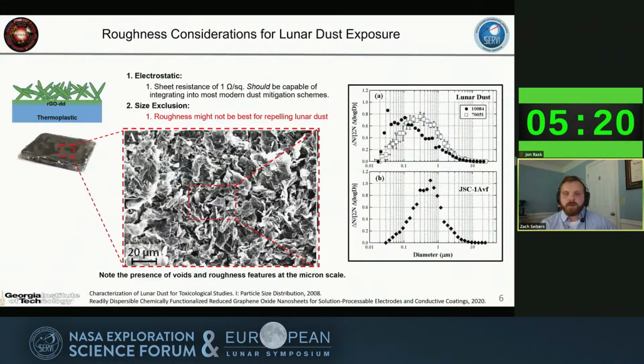So to the lunar dust issue. The voids on this surface are a very big potential problem, we think, in using this type of coating on a material in space. If you look at figure A here, this is the size distribution of lunar dust collected during the Apollo missions. And there's a region here that's sub-1 micron, so this is in the nanometer scale range. Basically there's a vast population of dust grains here that could penetrate these voids, get in there, and break up the surface. On the one hand, we have an electrically conductive surface, so we can get rid of the statically charged particles that we would expect to see in operations on the lunar surface. However, there's this size exclusion issue that we haven't really tackled yet.